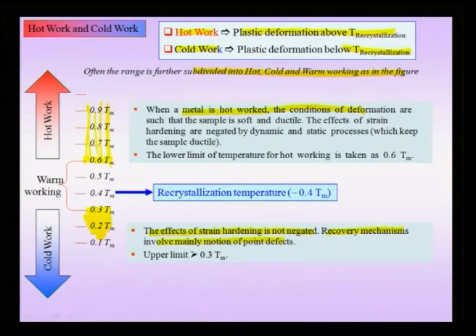When a material is hot worked, on the other hand, above this 0.6 Tm, in this high temperature regime, the sample remains soft and ductile. The effects of strain hardening are negated by dynamic and static processes which keep the material ductile. That means there are processes taking place while my deformation is happening. The lower limit of hot working is typically taken as 0.6 Tm. The temperature regime between the two, between 0.6 and 0.3 Tm, is often called warm working, wherein of course there is some amount of recovery and some amount of recrystallization taking place, but it is a regime between hot working and cold working.